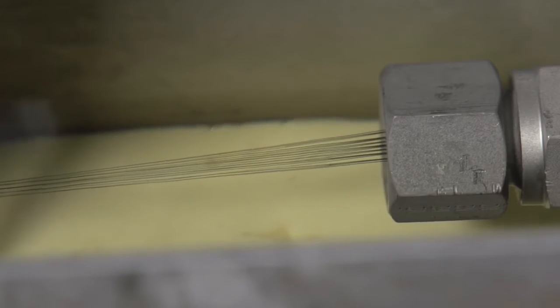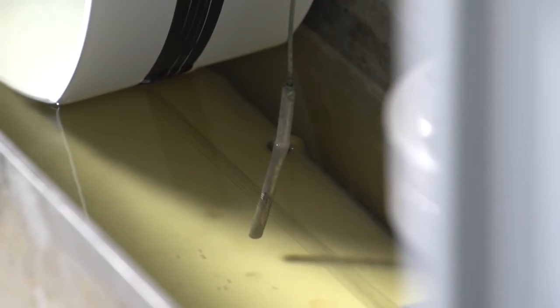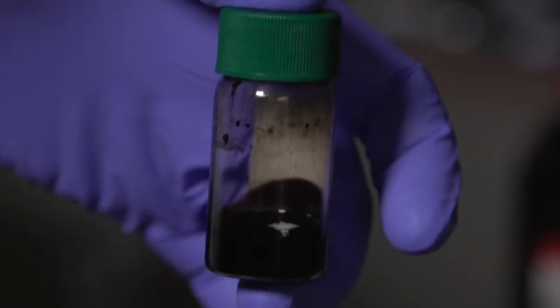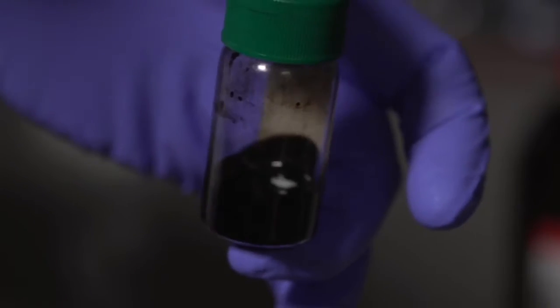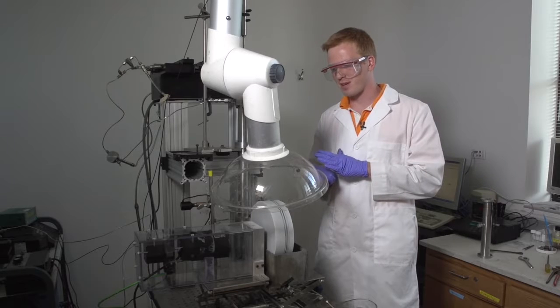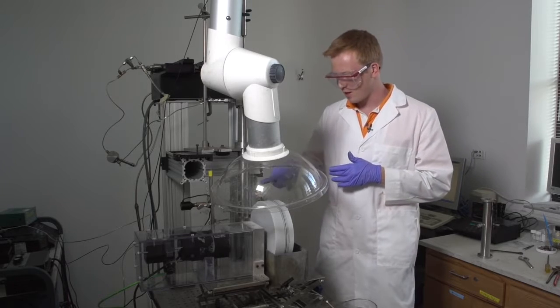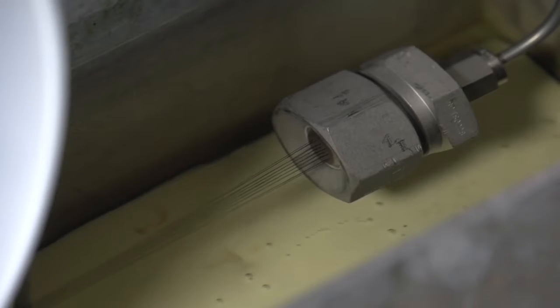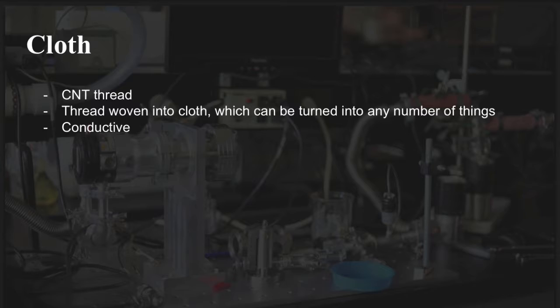So we have carbon nanotubes that are dissolved in a solvent, which is chlorosulfonic acid. And this solution is a very viscous type of material, so it's kind of like mayonnaise almost in viscosity. And we're extruding it through 19 small holes and then winding it onto a drum. These threads can be spun into cloth and be used to make things like clothing, sails, bridge cables, and even armor stronger than Kevlar. Because of the conductive nature of carbon nanotubes, all of these materials can be conductive as well, if needed. Otherwise, they can be coated in nanoinsulators for purposes such as safety.